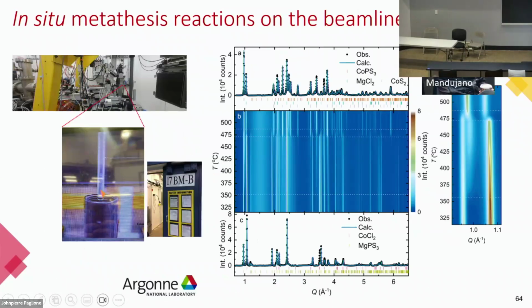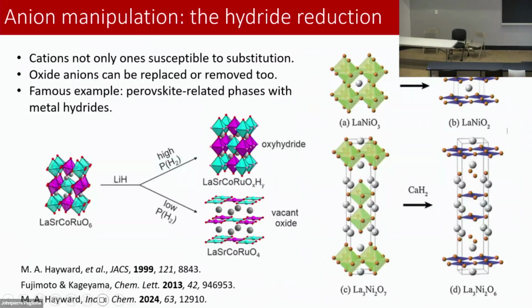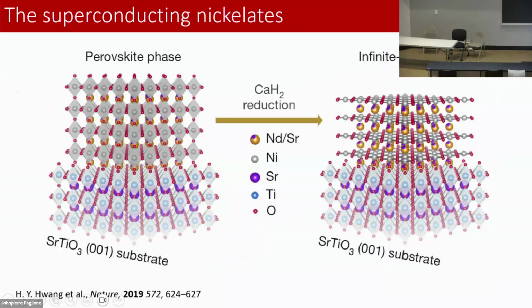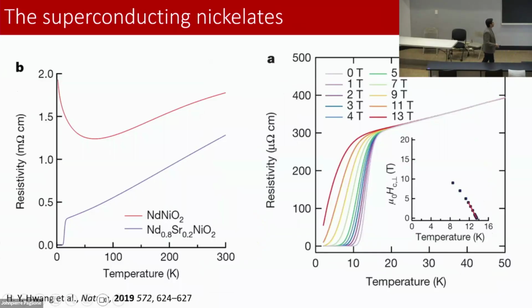All right. There are other kinds of techniques. One of the ones that I wanted to leave off on is this soft chemical technique where you react, say, a metal oxide like a perovskite or perovskite-related material with hydride. And you can make, as was discovered by Hwang and others, that you can make now, for example, nickel oxide that was a perovskite into an infinite layer, so it looks more like a cuprate now, right? It's 4-coordinate square planar geometry, and this was discovered to be a superconductor in 2019. You can see here the resistance curves.